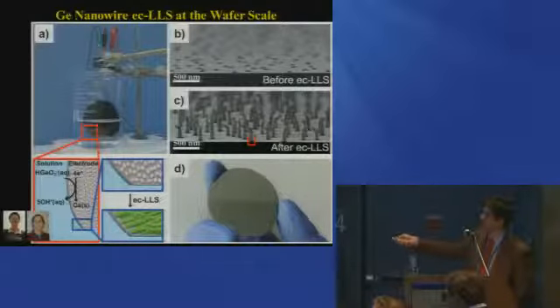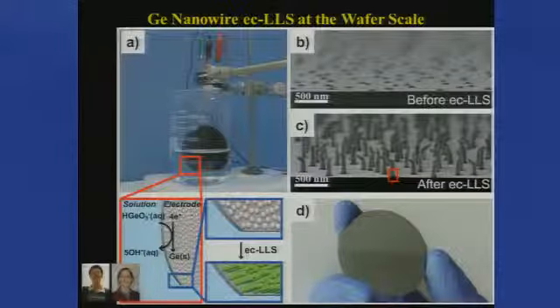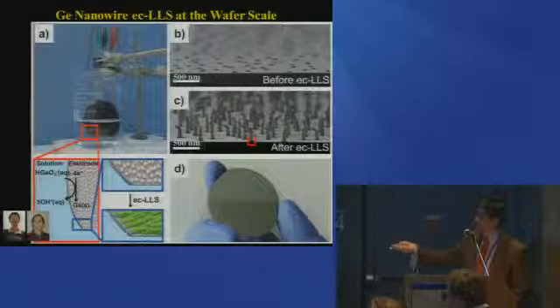Here's that picture again that I showed you, but now this is the experiment, and let me explain it. Our experiment here is to use our wafer as a support substrate for an array of liquid gallium nanodroplets, and that's what you're seeing here. These are prepared in a variety of different ways. We've done this either with very expensive MBE depositions, but these are also very easy to deposit electrochemically.